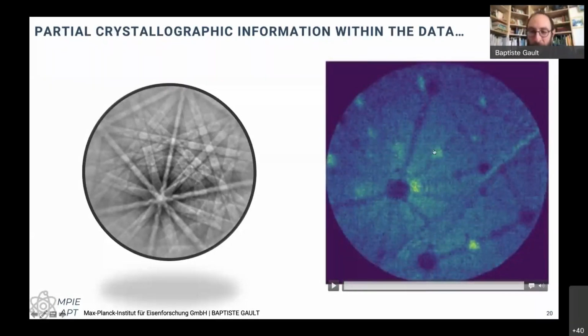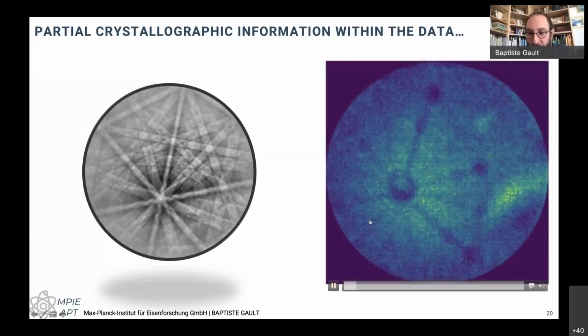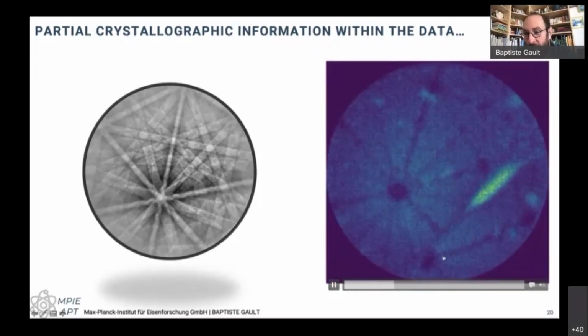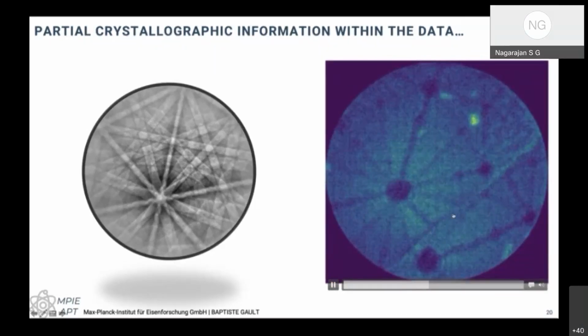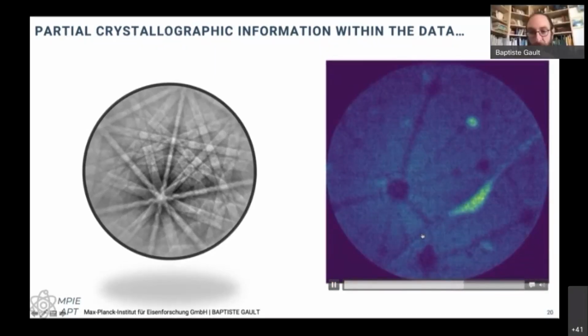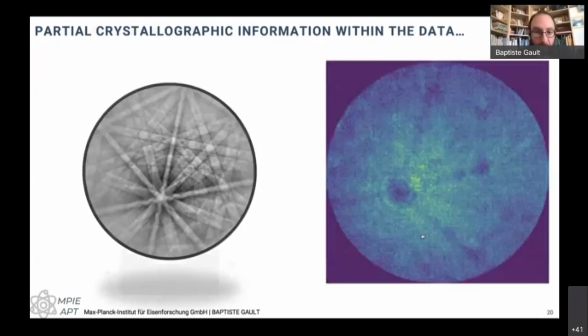And you can see some contrast here that pertains to the point density, which can be higher inside of precipitates, for example. So there's quite a lot of information in these maps that we can use. But here you can see clearly that we've crossed a grain boundary, and we'll be able to analyze this grain boundary in quite a lot of detail.